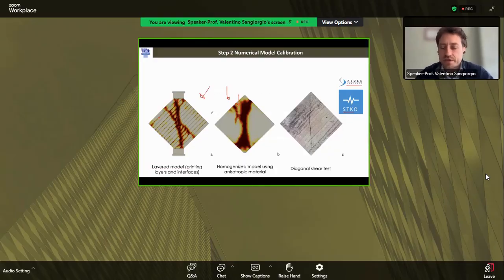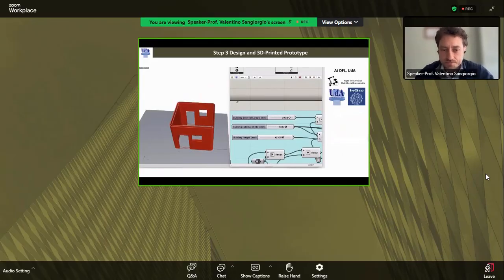The results were very similar, and so we decided to use the homogenized model because it is quick to achieve, and also the computational cost is lower than the layered model. The result is almost the same. And you can see here that the cracks that occur in the diagonal shear test can be simulated very well in the numerical simulation.